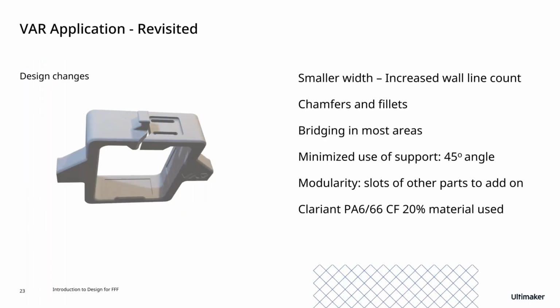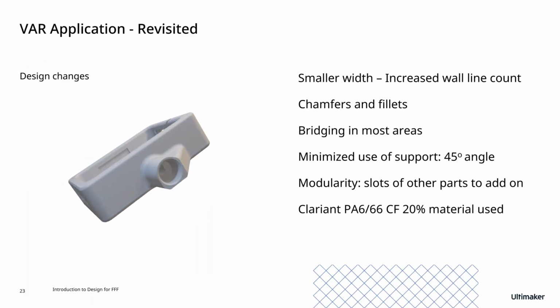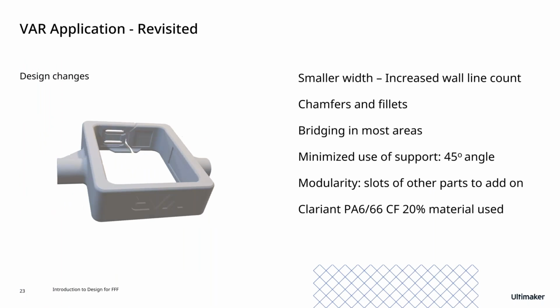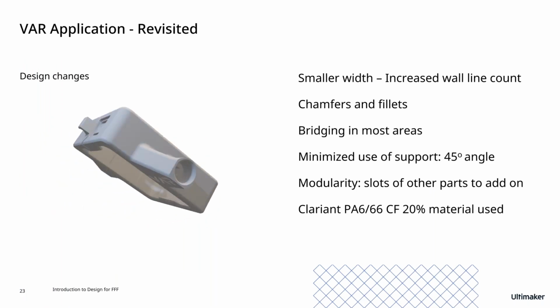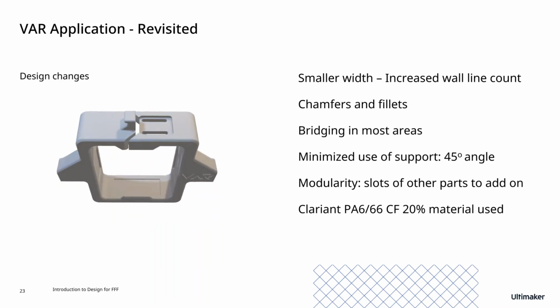At this time, I want to revisit the application that we started off with. Some of the design changes that we made: we had a smaller overall width of the tool and increased the amount of outer wall lines for more strength. In this webinar, we spoke about bridging, and bridging distance was used in multiple areas to print without support. Now, support is needed in some areas. One of them is the overhang on the right, and the overhang on the top, and then above this logo, there's a bolt that goes in on the side, and when printing, that needs support as well.